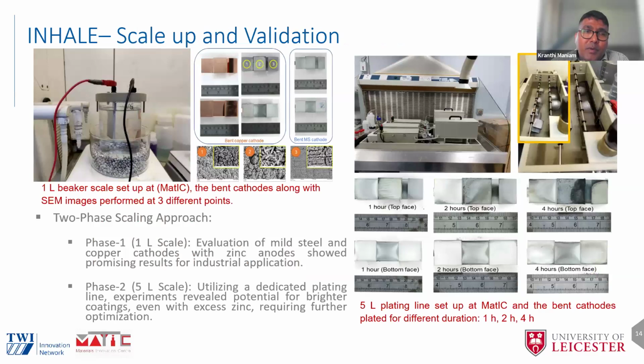So once we identified and got similar corrosion performance, having understood that the corrosion performance of the organic solutions is equivalent to the conventional systems, we attempted to go for the scale-up solutions, and that is where we tried first. Instead of going to 5 liters, we went with 1 liter, which you can see on the left, and instead of a flat part, we went with a bent cathode, because you will have a different mix of geometries, and the current density will be varying throughout.